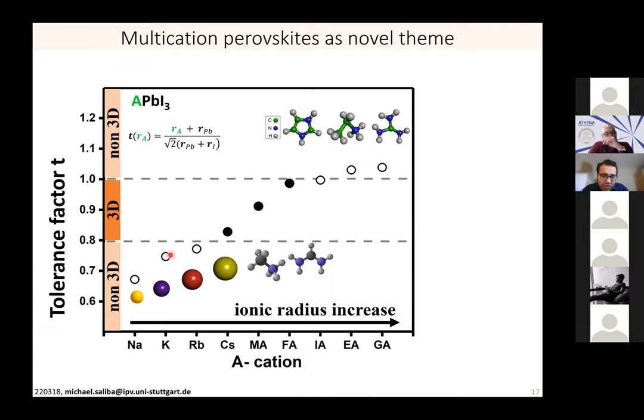Of course, it could be other components as well, but other components don't have the band gap that we require for photovoltaics. And you see it here, there are only three known cations which fulfill this relationship of being between 0.8 and 1.0 in terms of tolerance factor. It's only cesium, methylammonium, and formamidinium, and nothing else has been reported since the 1980s. And it's because the space is so tiny. When we go larger, here, for example, imidazolium, ethylamine, or guanidinium, it isn't a 3D perovskite anymore. So the octahedra separate from one another, the metal halide layers become distinct from one another, and we have what is called a 2D perovskite. If we go too small, there is the possibility of collapsing. So for example, the other alkali metals from sodium to rubidium are too small. So then we only have these three. We tried very hard to find others, but we haven't yet. So if you have an idea for a small molecule which can fit, we'd be all ears.